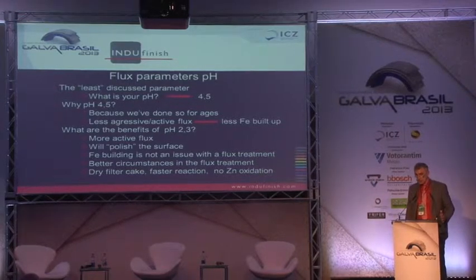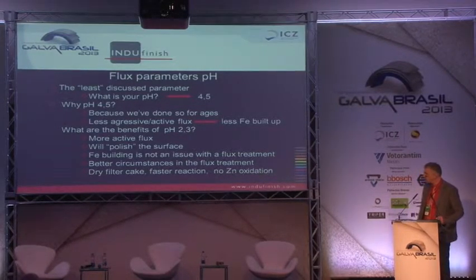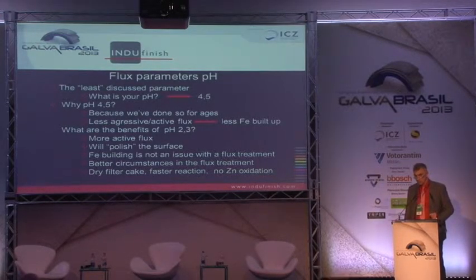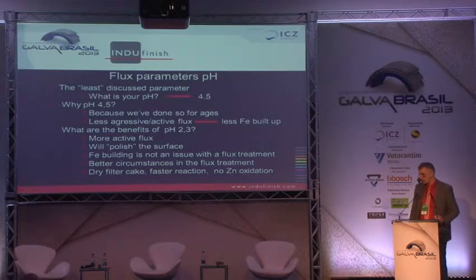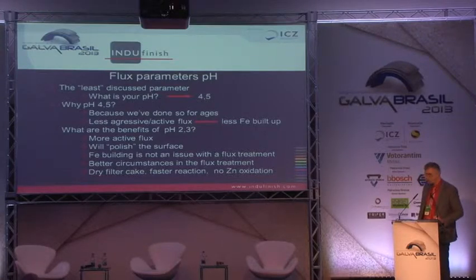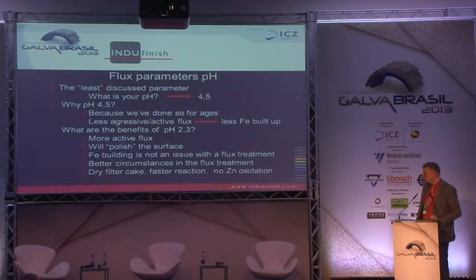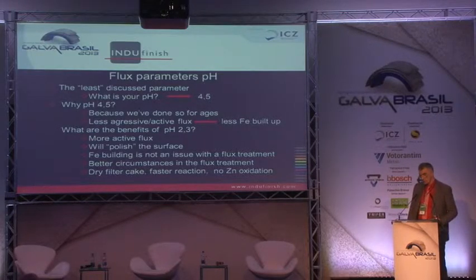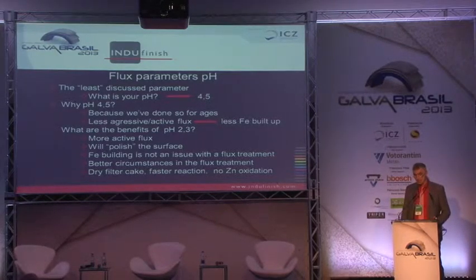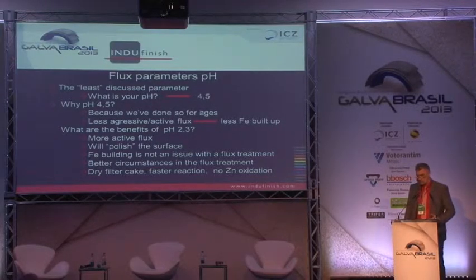Most galvanizers operate their flux fluid at pH 4.5. We did some investigation and nobody knows why. Even the suppliers of the flux fluid can't tell us why they are fluxing at 4.5. They simply don't know. But a disadvantage of flux fluid at 4.5 is that it is less aggressive, less active. I'm sure all your plants are in good shape and you have a good degreasing tank and 6 beautiful pickle tanks and your products are being well pre-treated.